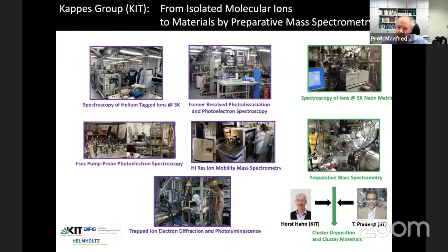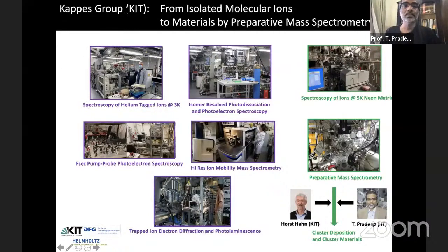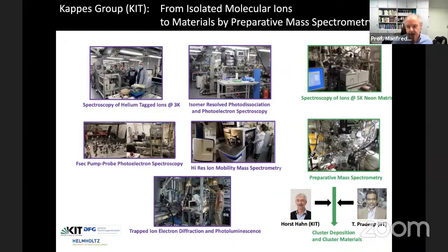Common to Pradeep is a high-resolution ion mobility mass spectrometry, which we also do. And we collaborate, in fact, on the cluster-cluster reactions, which you heard about a little bit earlier. Eventually, the ions that we collaborate on, we hope to be able to put into condensed phase environment. We have an experiment where we study ions in neon matrix. So we soft land into neon, do spectroscopy in neon. And we have a what I call preparative mass spectrometry, which we have used in my group to study fullerene materials, for example, other isomers of C60, which one can separate and deposit,